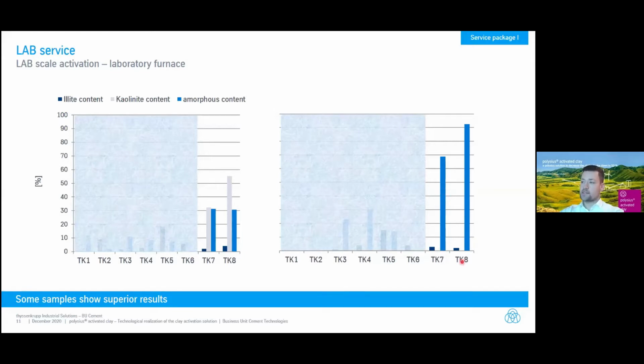And this is the same for the sample TK8. So we are pretty well able to activate this kind of clay in our flash device. And we are able to transfer all the kaolinite into active phase. So this is a highly reactive activated clay, which you see here on the right-hand side.